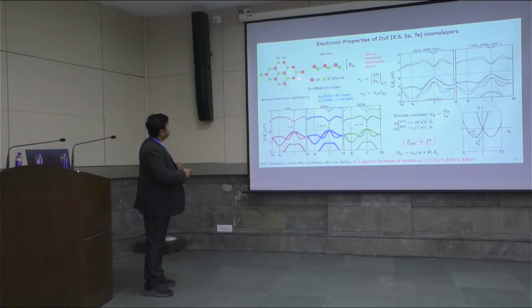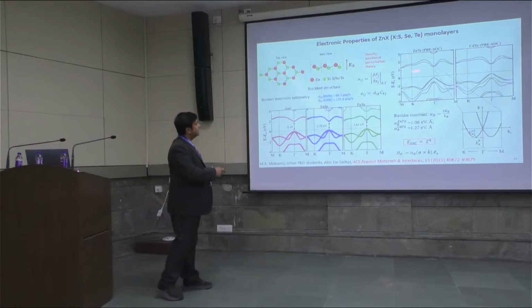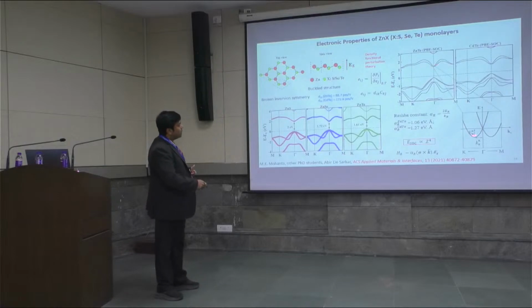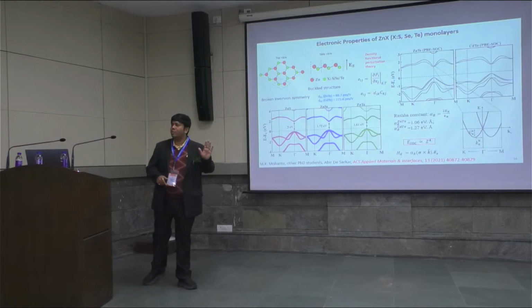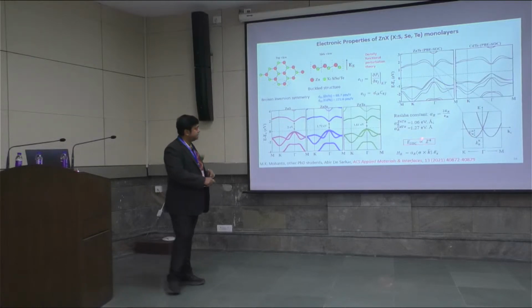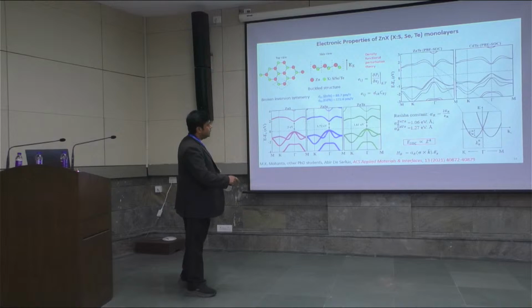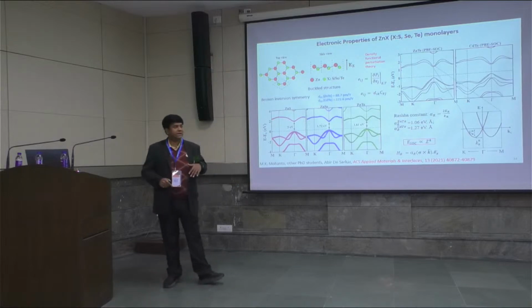And because of this polar buckled structure, as I have been mentioning to you, an out-of-plane electric field intrinsically arises, which induces momentum-dependent spin splitting in the conduction band, as you can see. So one parabola splits into two parabolas. This is the momentum-dependent spin splitting, and this is the Rashba constant. And you need a high Rashba constant for spintronics applications.